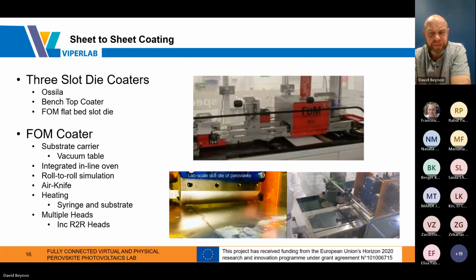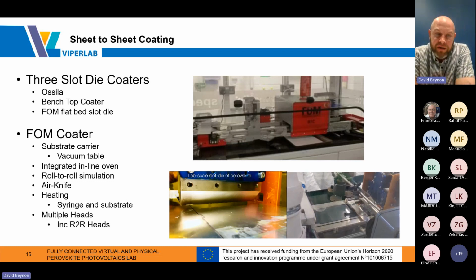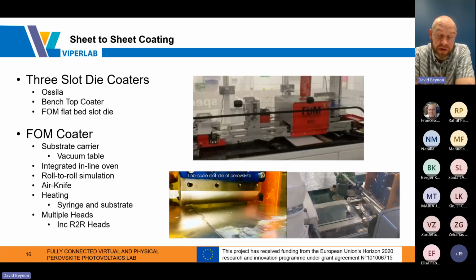We have what we call the benchtop coater, and a flat bed slot die coater. And within that, the flat bed coater can coat up to 10 centimeters wide by 25 centimeters long. We have a substrate carrier we've modified to have a vacuum table in line. Quite important for being able to get uniform, repeatable films. It has an integrated oven in line, and with that we can do a roll-to-roll simulation. So we can program it to understand what our roll-to-roll line would be like. So we'll then modify the speed that the substrate passes through the dryer to replicate the residence time of the roll-to-roll system.